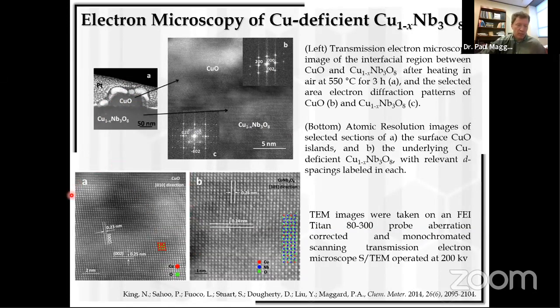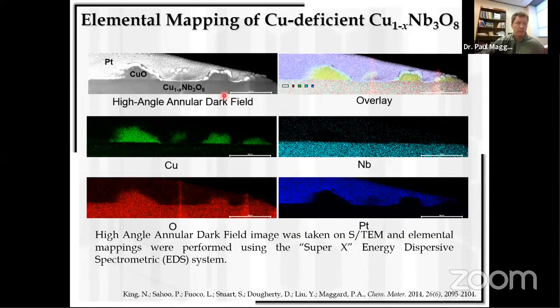And for this one, for example, we have the 010 direction of the crystalline structure oriented above the substrate of the 138 phase. And then if you image the 138 phase, we have the 103 direction imaged here. And all of these we're taking on TEM. With compositional analysis, it's also highly apparent, right? So here we've deposited the platinum on top of it just to be able to pick it up off of the base, and to image it.